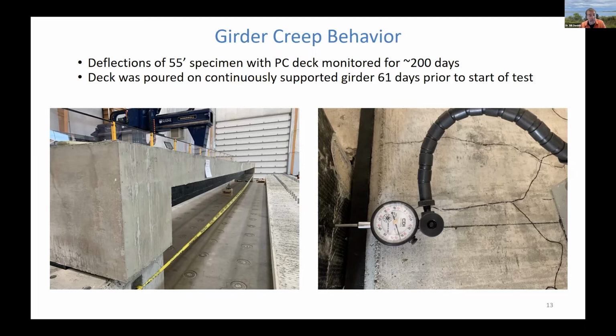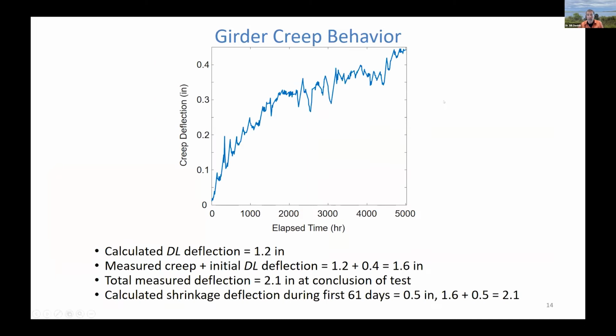And by coincidence, or not coincidence actually at all, that is the same girder that we tested to failure in a strength test after we were done with the creep test. And I showed the video of that test in the last presentation. So this is the same beam. It first underwent these creep deformations. And this is what we observed. So this is a plot of creep deflection versus elapsed time over that roughly 200-day period.